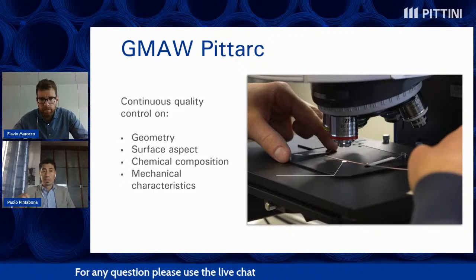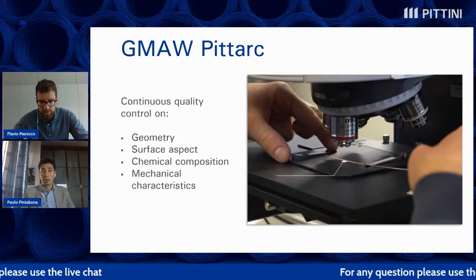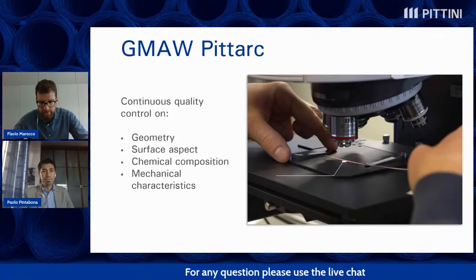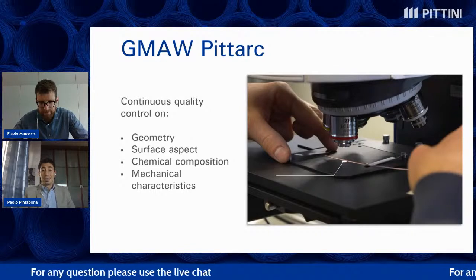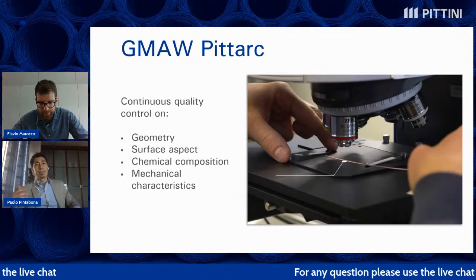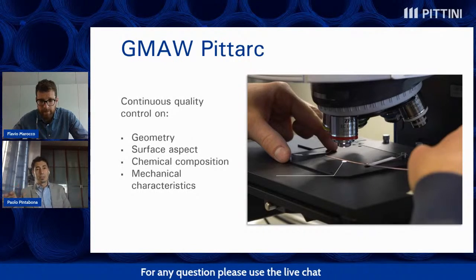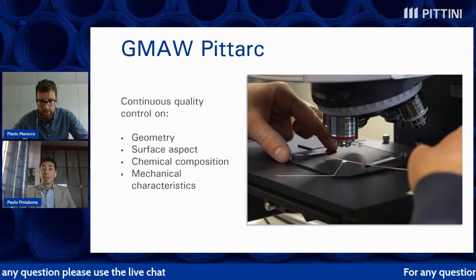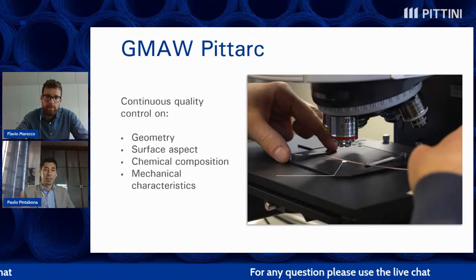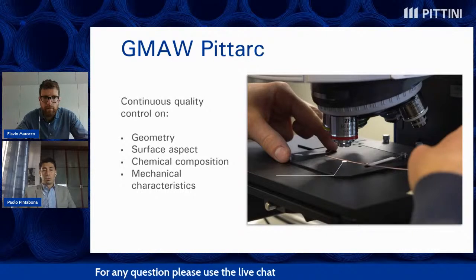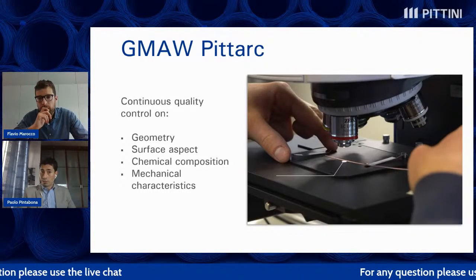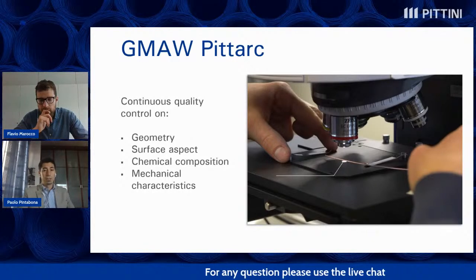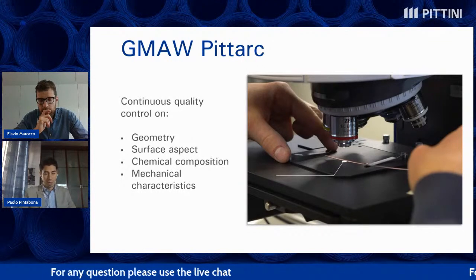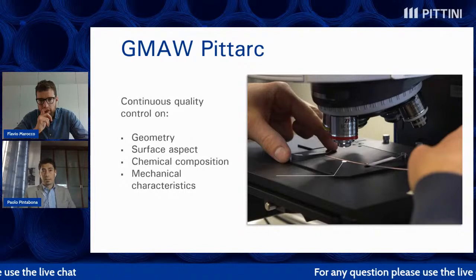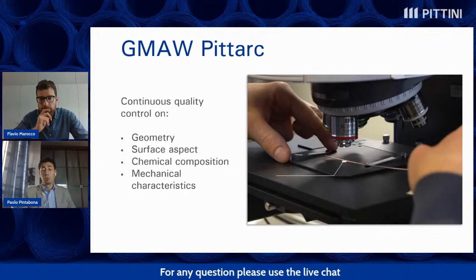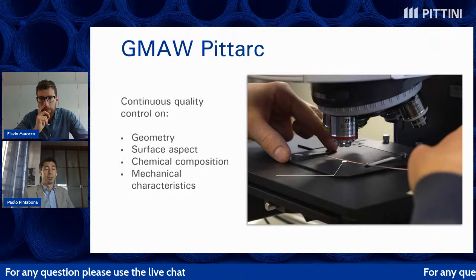Then, as very important, the chemical composition, and so controls are made by means of analysis with a spectrometer, and in case it's needed, to have more details, especially on small diameter wires, specific recordings are made for elements such as sulfur and carbon. And at the end, also absolutely important is the check on the mechanical characteristics. So the wire is subjected to a tensile test to find its tensile strength. And of course, welding tests are also carried out in Pittarc to verify strength, resilience, and elongation.